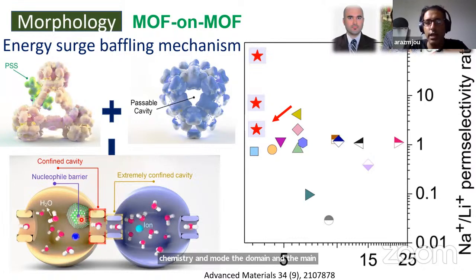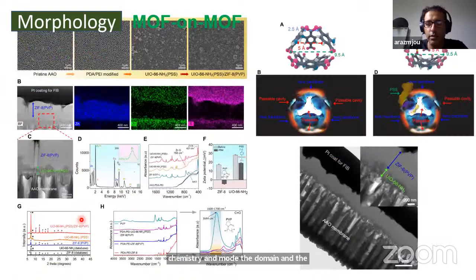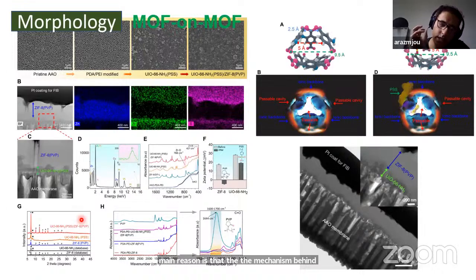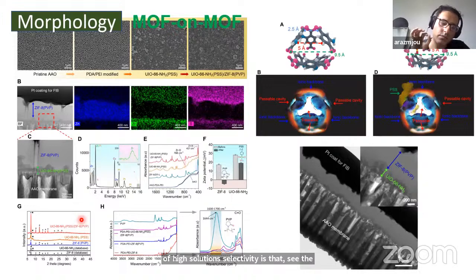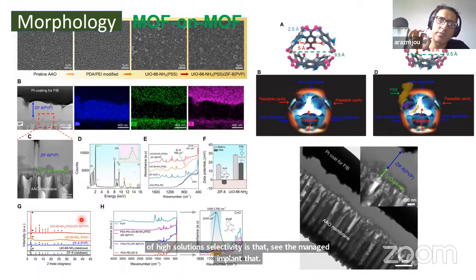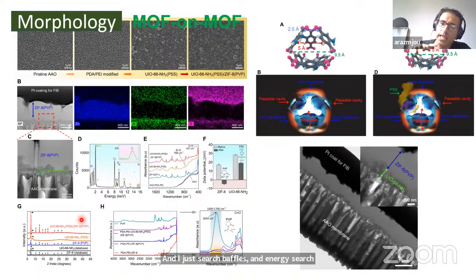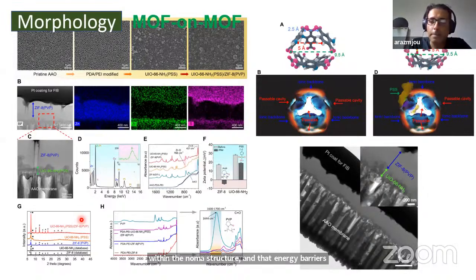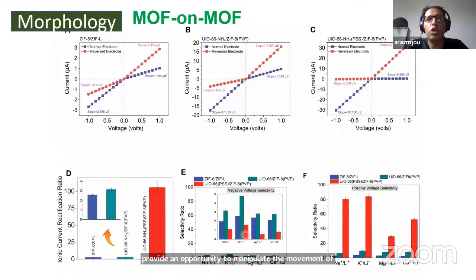The main reason is that the mechanism behind this high lithium selectivity is that we managed to implant energy barriers and baffles within the nanostructure, and those energy barriers provide an opportunity to manipulate the movement of ions selectively. As you can see, our membrane not only showed good lithium selectivity, but also showed rectification. Ionic rectification is very critical